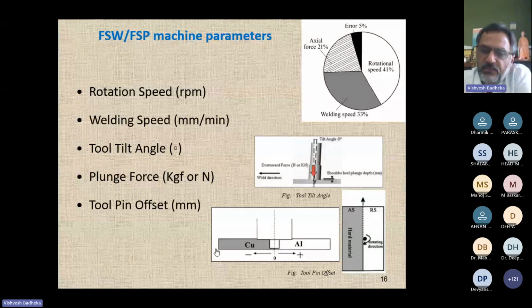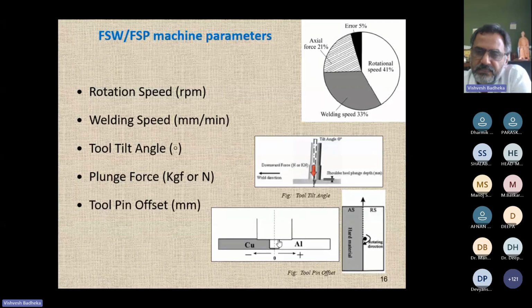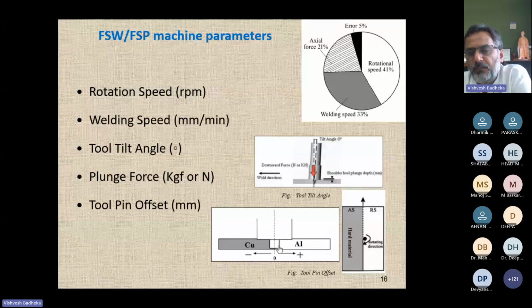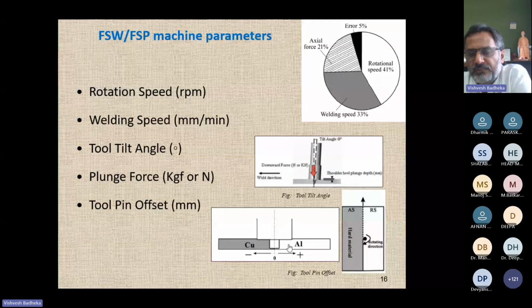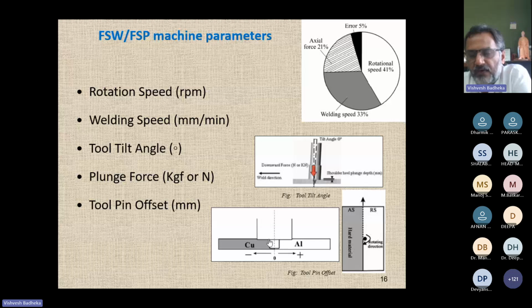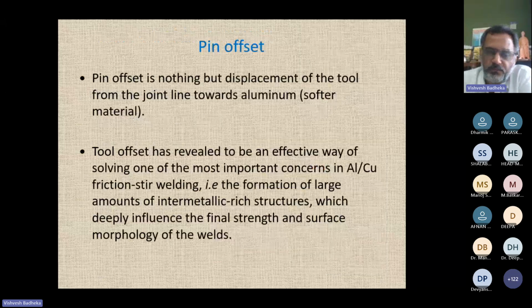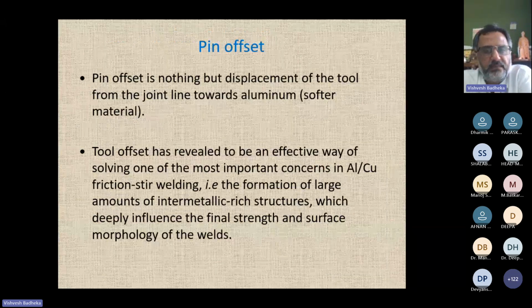So currently, normally if you go with aluminum, copper, you go with the zero offset. You plunge the tool exactly at the center. But whenever there are dissimilar metals, you need to plunge the tool more on the softer side, right? The contact with the harder material should be minimum. This offset method will help you to control the intermetallic formation. So this is the explanation given here in the next slide.